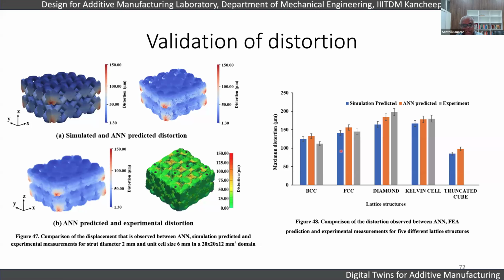Since it takes the input of both the experimental data as well as the physical data, it is able to work closely in the nominal zone of dimensions, so reduced error and reduced order models are used. You can see that this is a typical strut diameter of 2 mm with a unit cell size of 6 mm in a 20 by 20 by 12 mm cube. So it is a relatively small part, but for a large part, even these distortion levels could be much higher.